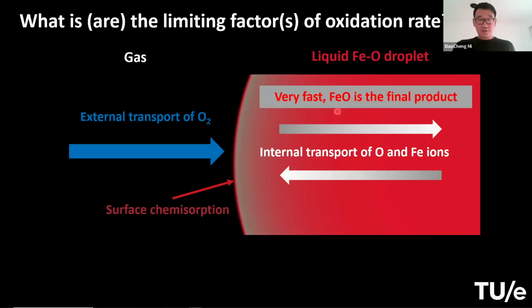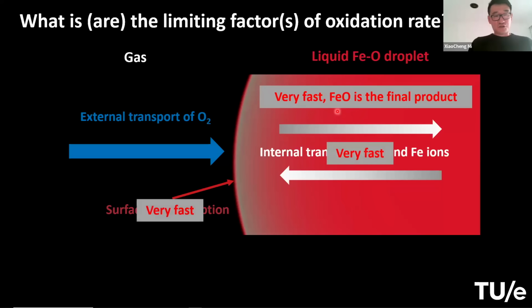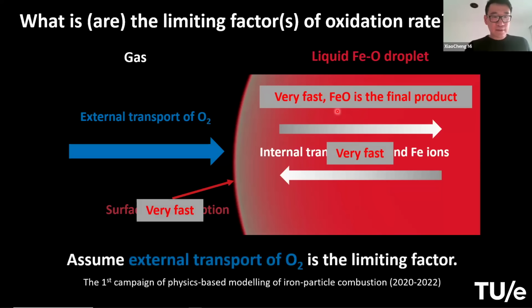But we know that in liquid phase, they are in ion form, so this reaction is very fast. Also, we assume that at this very high temperature, the internal transport and the surface chemisorption can also be very fast. So in the very first model that we have for liquid phase iron combustion, we just assume that external diffusion is the only rate limiting factor. And how well does this model do? Let's see some results.